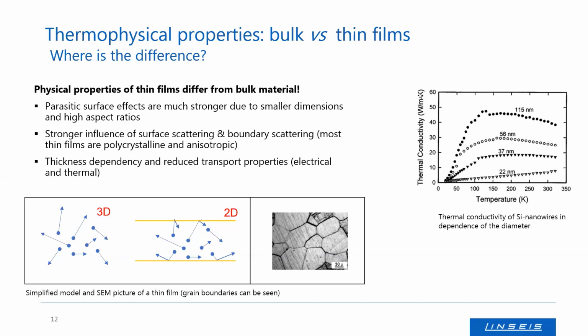On the right-hand side, you see an example. We show the thermal conductivity as a function of temperature, in this case for silicon nanowires, so for one-dimensional objects. And depending on the diameter of these nanowires, the thermal conductivity changes dramatically. For very thin wires, it's lower than 10 watts per meter Kelvin. For thicker wires, it goes up to 50 watts per meter Kelvin. So you really have to measure the thermophysical properties of the thin film, and you can't just take the values from the bulk material.